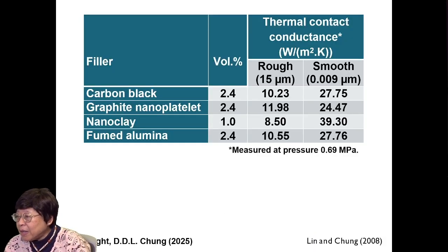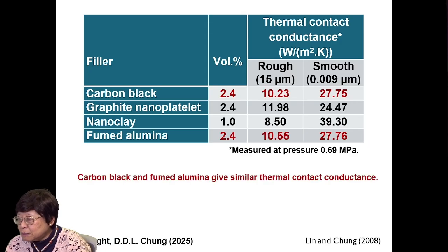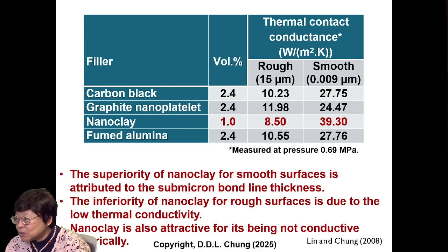Here it compares the thermal contact conductance for these 4 fillers: carbon black, graphite nanoplatelet, nanoclay, and fumed alumina. Carbon black and fumed alumina give similar thermal contact conductance, as you can see, for both rough and smooth surfaces. Nanoclay, in red, the superiority of nanoclay for smooth surfaces is attributed to the submicron bond line thickness. The inferiority of nanoclay for rough surfaces, as you can see, is due to the low thermal conductivity. Nanoclay is also attractive for its being not conductive electrically.